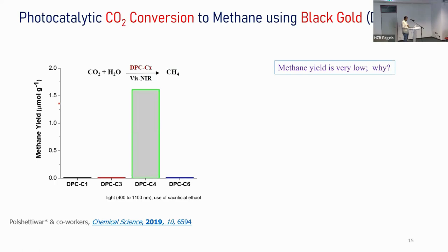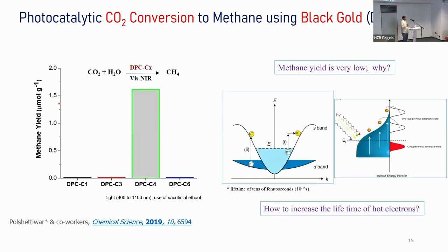And the reason, what we thought about, is that it's not only about harvesting the solar photon, but it's also about the lifetime of the hot electrons, right? Once you generate these excited electrons, they need to get injected into the reactant rather than recombining. And it looks like the electrons are recombining with the hole, and you're not able to transfer the electrons. So now the question is, how to increase the lifetime of these electrons?